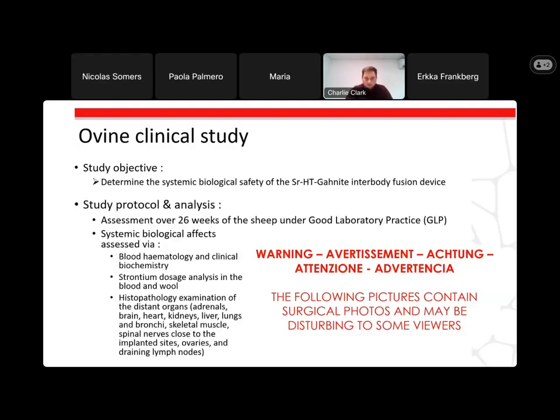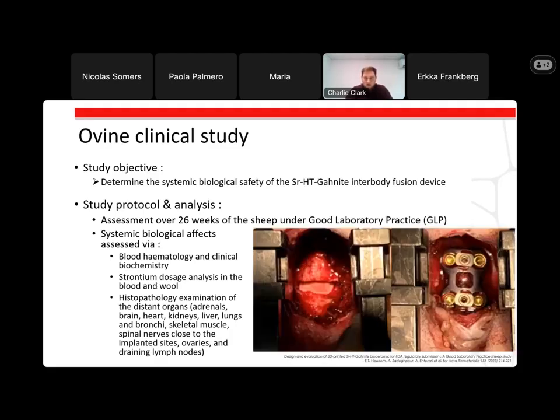So this was an assessment over 26 weeks of the sheep under GLP, using parts that we had printed with their powder on our machines. So they were looking at all the different biological effects. And as we can see here in the picture, this was the implantation of, on the left, just the spinal cage, and then on the right was an extra device that was added on top to keep the vertebrae in place just for the test.